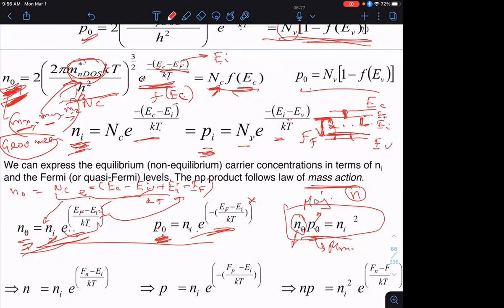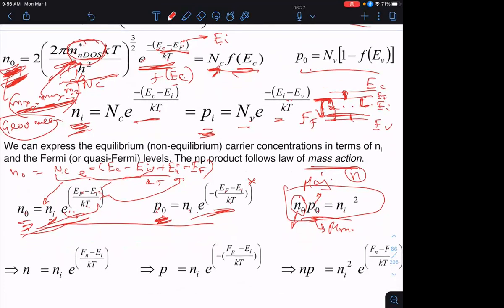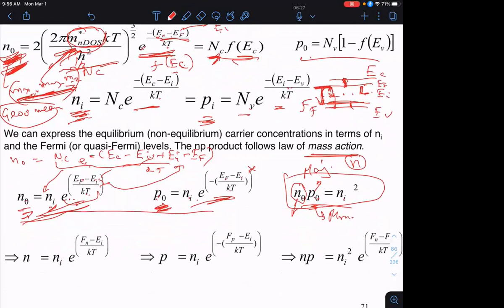And then to calculate density of states, which is used for calculating electron or hole concentrations, you have to take the geometric mean of those band curvature masses. In the next class, for conduction, we'll see you have to take the harmonic mean of the effective masses. I'm sorry, there are so many masses floating around. I'm sure your head's spinning, and it's pretty confusing when you see it for the first time.